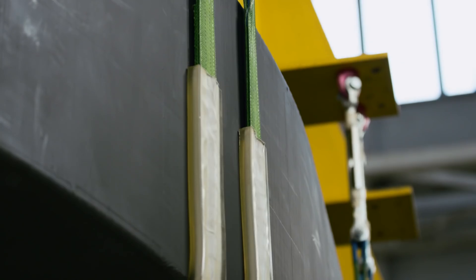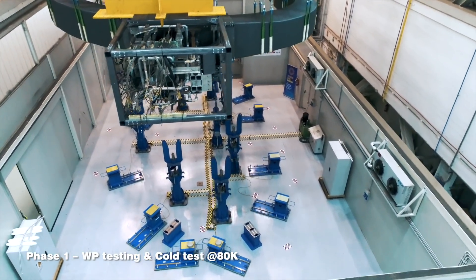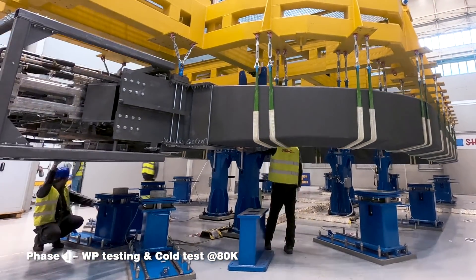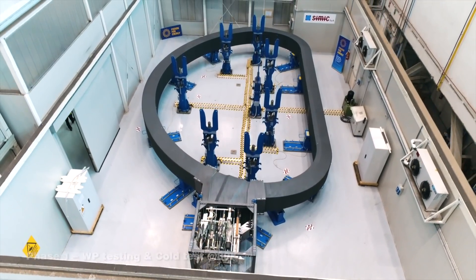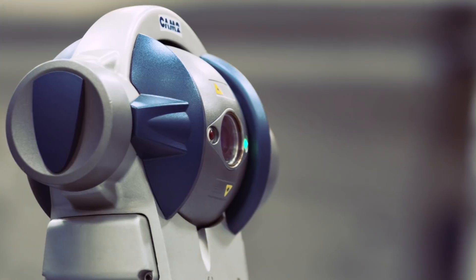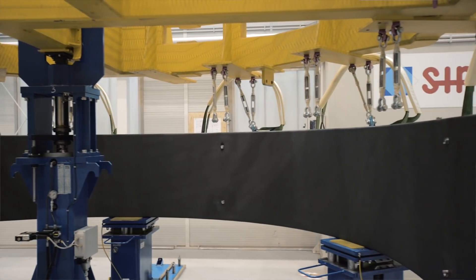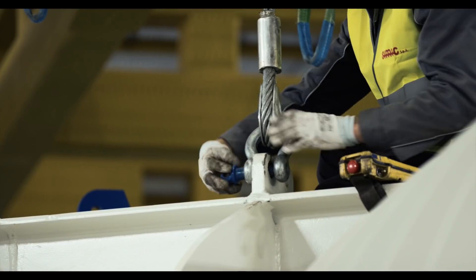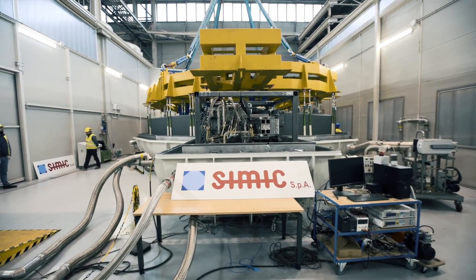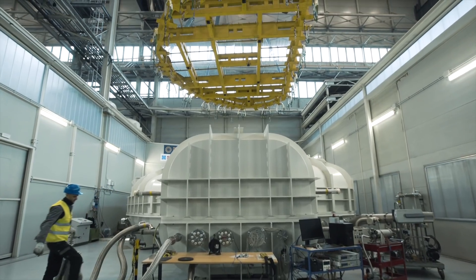The TF coil manufacturing starts with the receipt of the large superconductive magnets called a winding pack, weighing 120 tons and measuring 9 by 16 meters. A full dimensional inspection is performed by the most advanced technologies. DC and AC electrical tests and a pressure test of the cooling channel are performed before moving the winding pack into a large vacuum vessel for testing. A leak test at 30 bar is done before starting the cooldown for testing the magnet in cryogenic conditions.